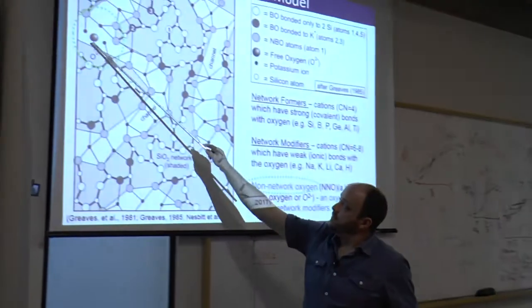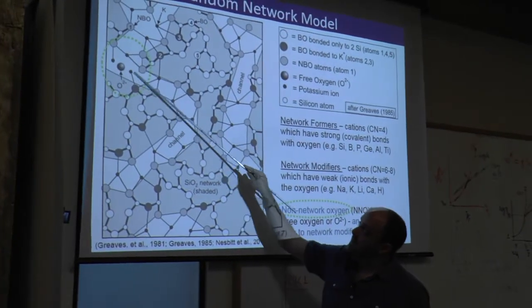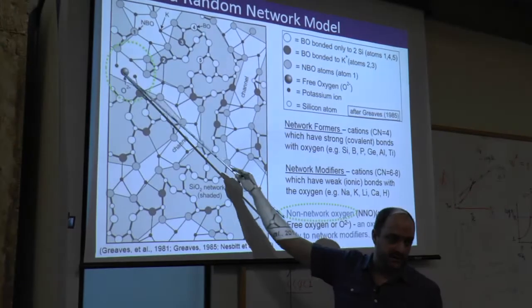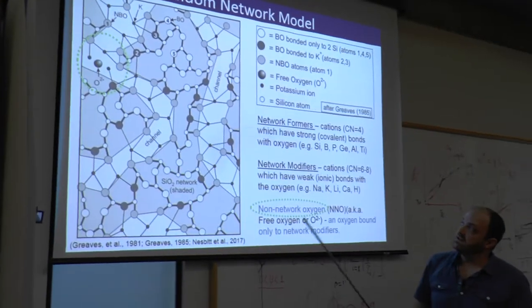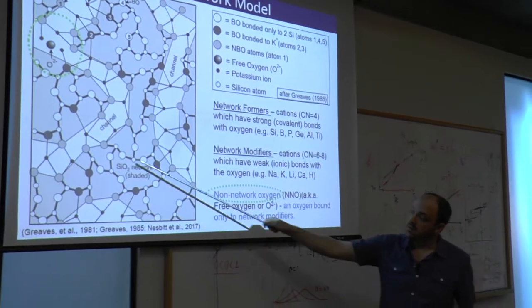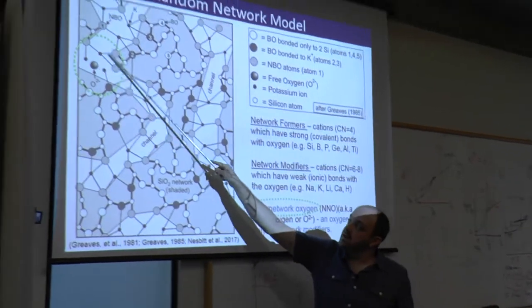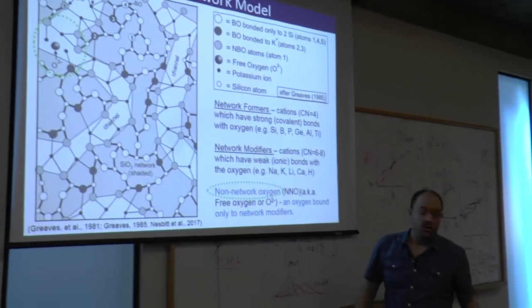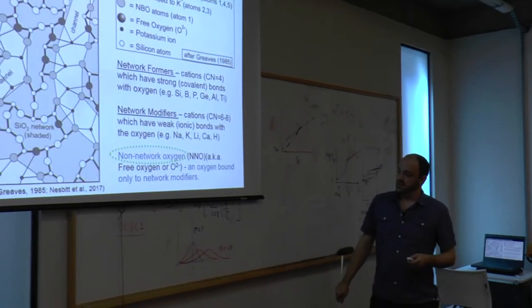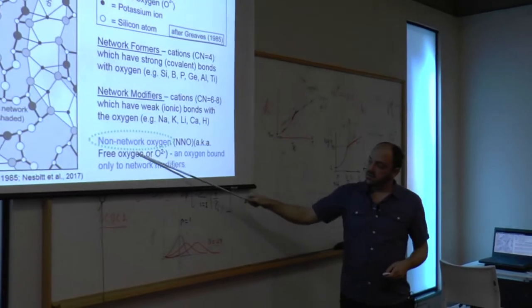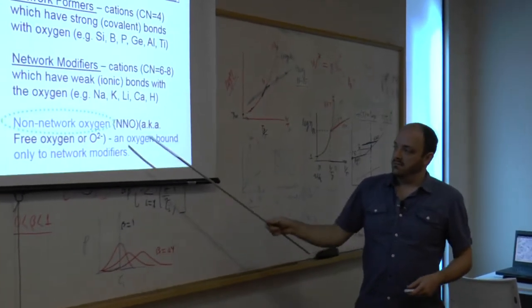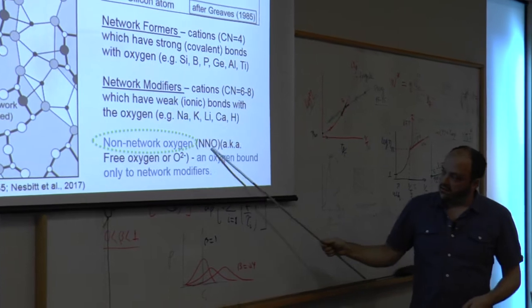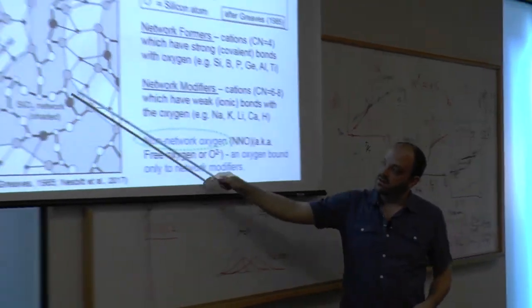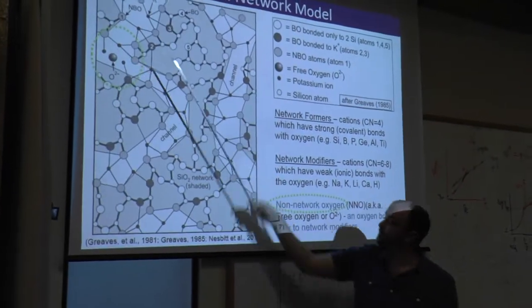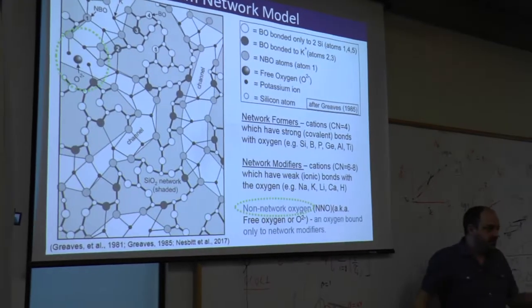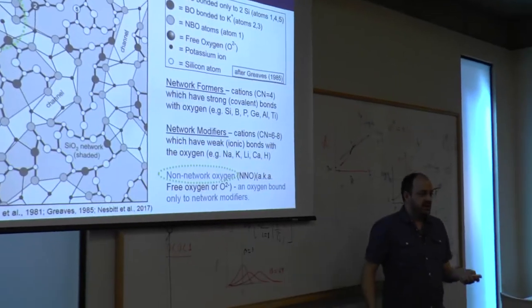Some of the oxygen in the network might only be surrounded by sodium ions. So this is oxygen that's not bound to the silica part of the network. It's just held in the network by these weaker ionic bonds. They term this free oxygen or free oxide. Other people have called it non-network oxygen because it's not part of the silica network. It's sitting in these channels. So whatever name you prefer, it doesn't matter. Just define exactly what you mean.